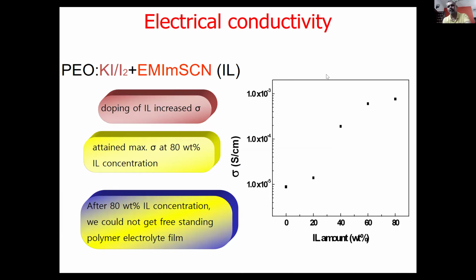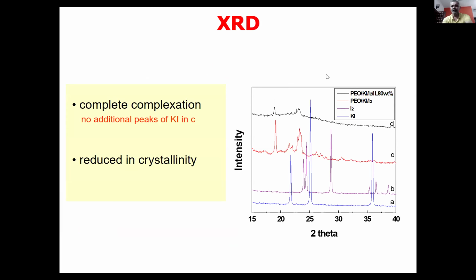And we have found that if you put ionic liquid, your conductivity goes very high. Another characterization tool, these machines, is known as X-ray diffraction pattern. And this machine says that if you put ionic liquid, you can get a very good high ionic conductivity by reducing crystallinity, crystalline and semi-crystalline.